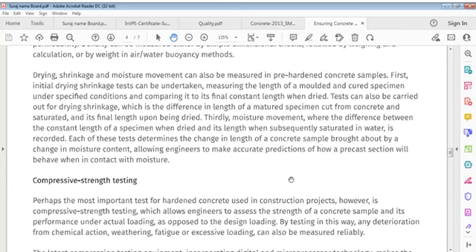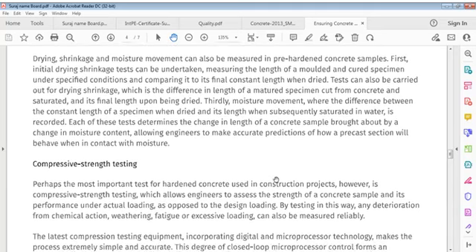A test can also be carried out for drying shrinkage, which is the difference in length of a matured specimen cut from concrete and saturated, and its final length upon being dried. Thirdly, moisture movement, where the difference between the constant length of the specimen when dried and its length when subsequently saturated in water is recorded. Each of these tests determines the change in length of a concrete specimen brought about by a change in moisture content, allowing engineers to make accurate predictions of how a precast section shall behave when in contact with moisture.